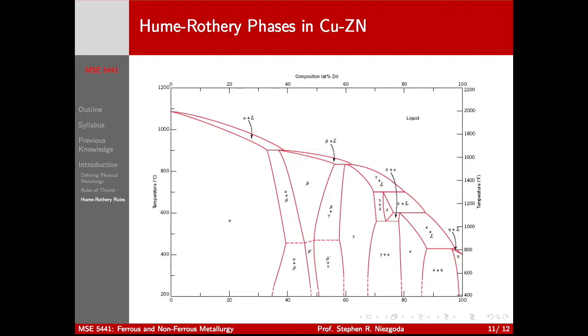So what crystal structure is copper? FCC. What about zinc? HCP. So by the basic rules of thumb, should there be any significant miscibility between copper and zinc? Not really, but even at room temperature, you can develop 35% zinc in copper. And then you get these islands of stability. So now we've got a miscibility gap, but now I've got a stable single phase here, another miscibility gap, a stable single phase here, another miscibility gap.